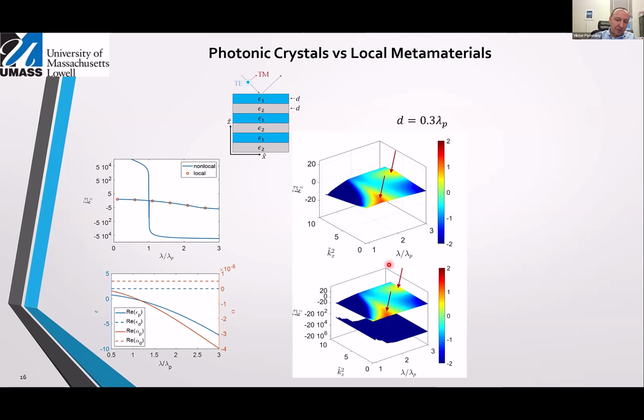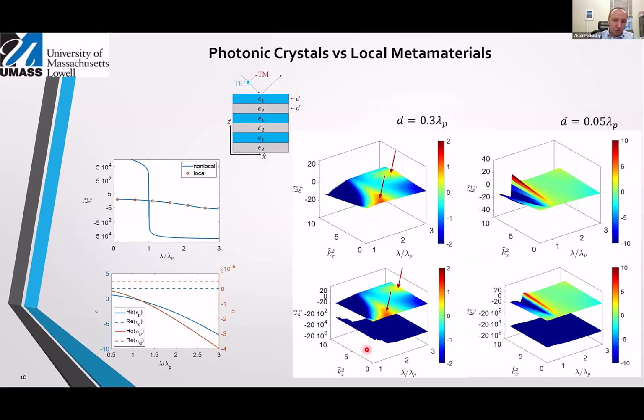This is what would happen if you add non-locality. You have that same dispersion of the main wave, and then you add an additional wave that again has a humongous negative index squared. So therefore it evanescently decays inside your composite, and really it doesn't matter. Now, you make the material smaller. I showed you that you should converge to a metamaterial.